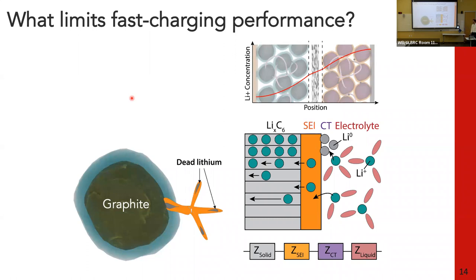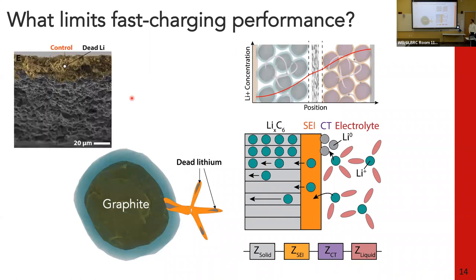And you can't strip it all back. You get what's called dead lithium. And that piles up on the surface of your electrode and essentially kills your battery. So you don't want this to happen. So all our EVs are essentially controlling the charging rate to avoid this happening. This is why you can charge faster at low state of charge, but then you have to taper off towards the end because you're approaching the potential or the energy level of this metallic lithium. So you can't drive the cell as hard when you get closer to this end point. Okay.